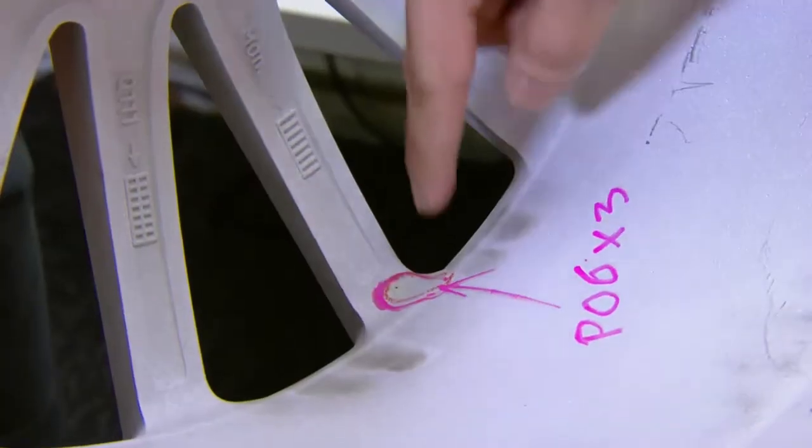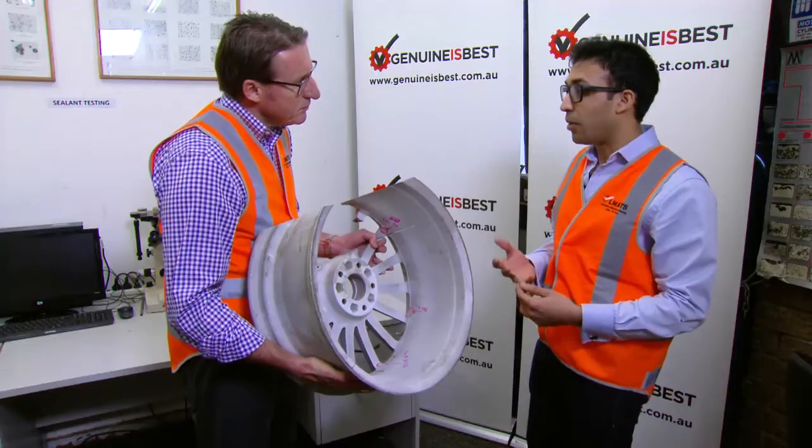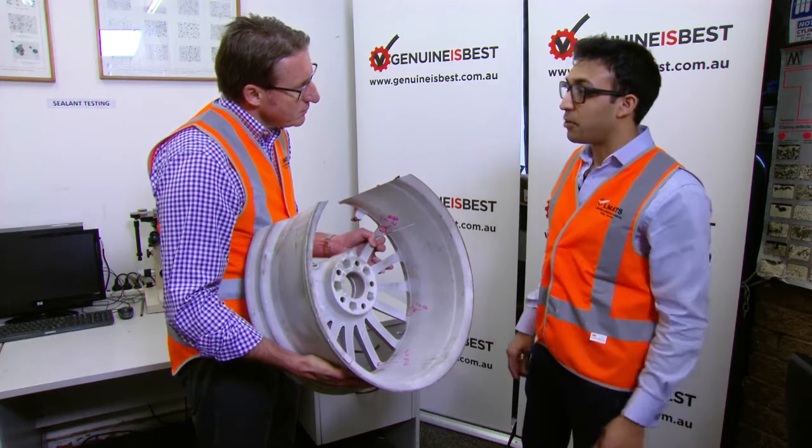So Yashwin, what does that cause? These poor manufacturing conditions led to major porosity in the wheel, and you can actually see those pores with the naked eye. Poor manufacturing conditions also led to other defects like hot tearing, and micro and macro pores visible in the metallographic analysis — causing serious weakness in the fake wheel.